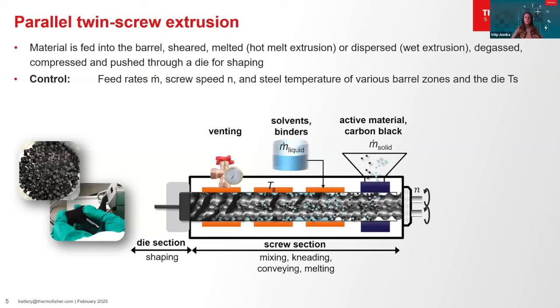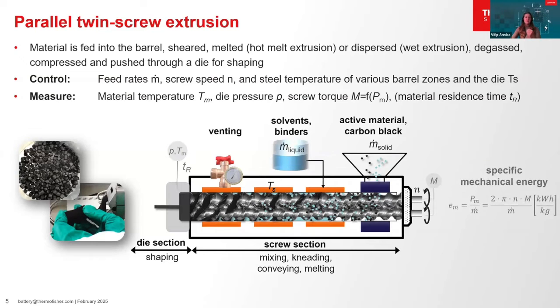The parameters to be controlled include material feed rates, screw speed and the temperatures of the various barrel zones and the die. These settings influence the measurable parameters such as the material temperature and the pressure in the die, as well as the screw torque and the material residence time. An important process parameter is the specific mechanical energy input, or SME, which is calculated from the power required for the mixing or the torque that applies to the screws.